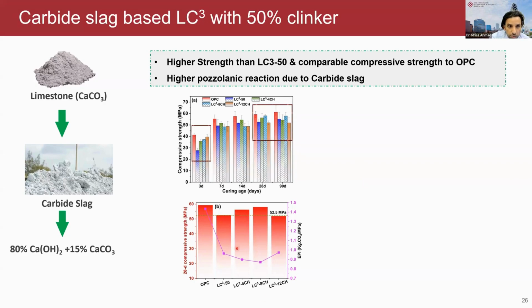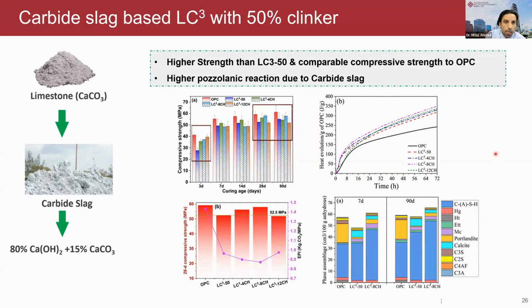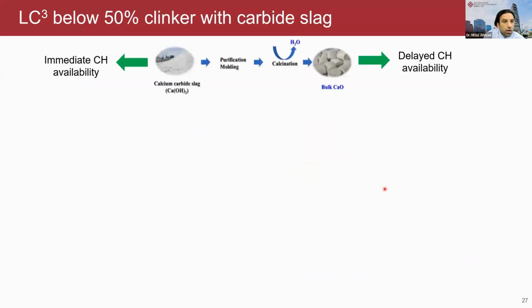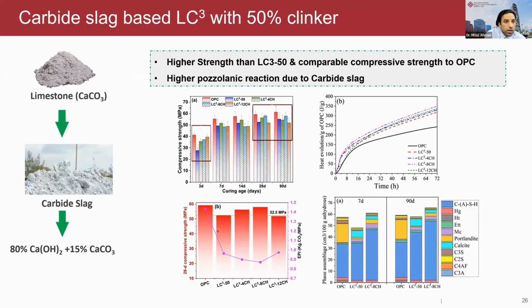Besides that, the second picture is related to the environmental performance index. As compared to LC cube 50, this LC cube CH cement has a slightly lower environmental performance index. Why does it happen? We observed that this calcium carbide significantly improves the reaction of calcined clays, and the binding gel volume was significantly increased in this system. So that was a system where we replaced only 50% clinker.